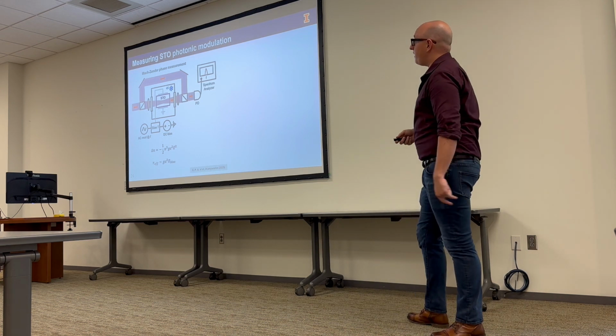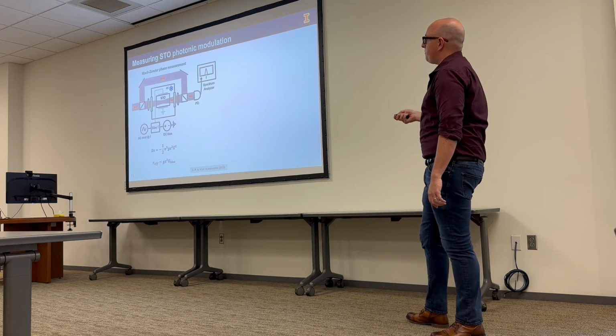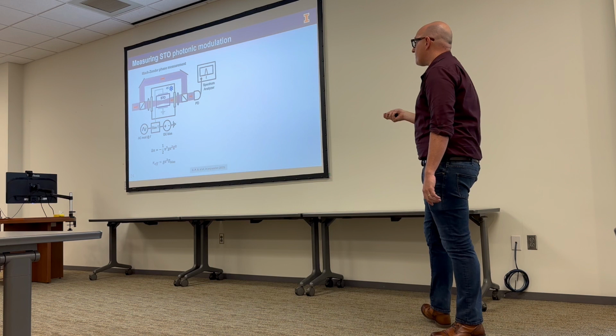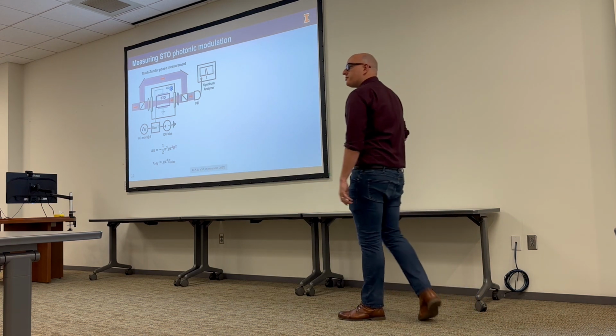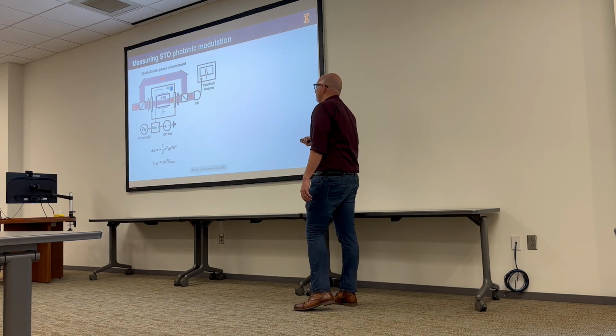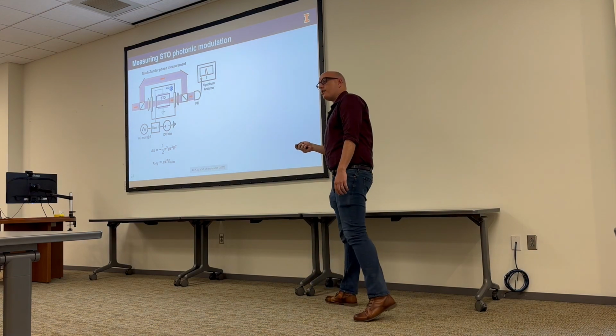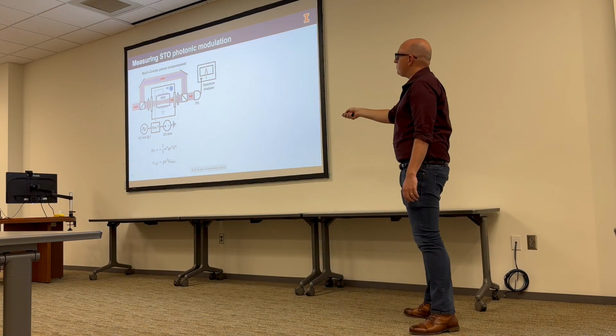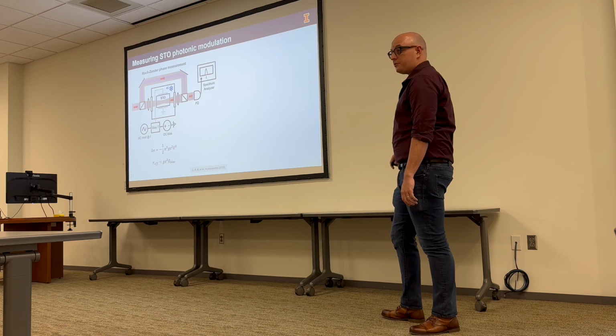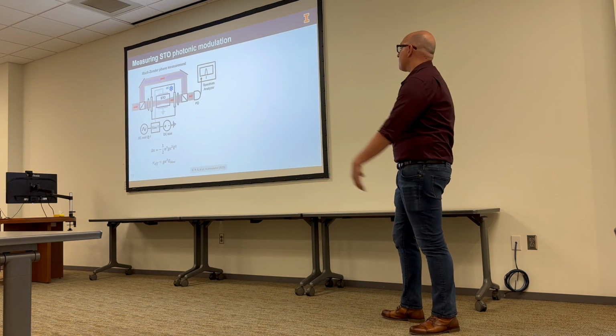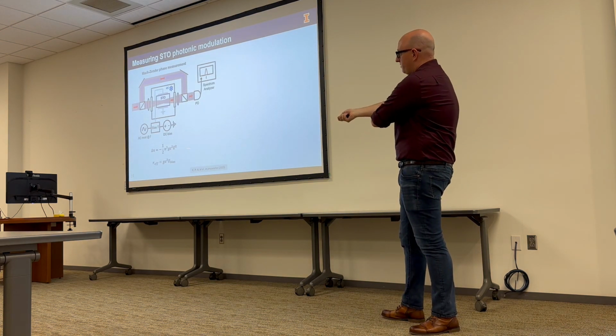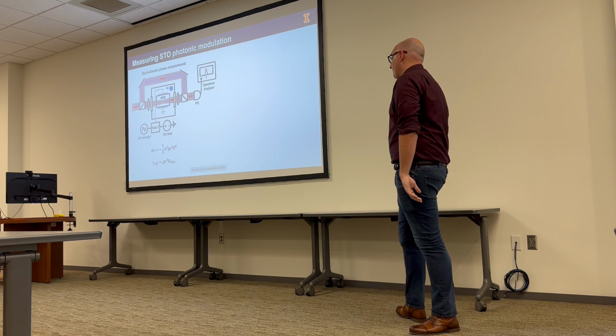And so we can actually do this and measure. We can take a piece of strontium titanate, put it in a cryostat, bias it, and measure its index of refraction change by putting it in a Mach-Zehnder interferometer, where we encode the phase change induced by the material as basically an amplitude change in the output of this interferometer. This is once again a quadratic electro-optic effect, so we have to bias it, but once again, epsilon's huge and we have to square it, so this effect can become quite large.